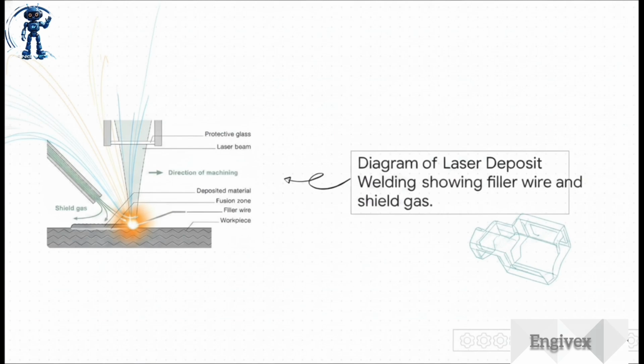And laser technology isn't just about joining two flat sheets together. It's also used for building up new material from scratch. In laser deposit welding, sometimes called direct metal deposition, a laser beam rapidly heats the surface while a filler wire, or sometimes a powder, is fed directly into the molten pool, all under a protective shield gas. Because of the rapid heating, rapid cooling, and totally precise energy control, we can create metallurgically bonded layers perfectly suited for repairing surface defects, or even better, for additive, near-net shape manufacturing of brand new parts.